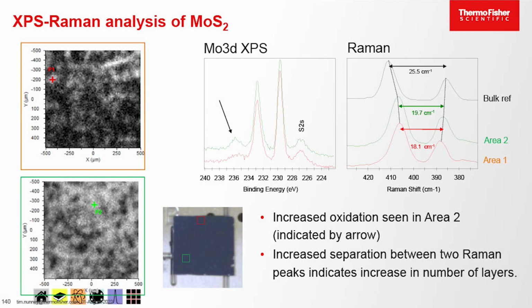So if we have a look at another area on the sample, so this is our original area here in red, and this is another area down here, much more signal down here. We can see much more, but we see a larger separation in the Raman spectra for the separation of those two peaks. So we've gone from 18 wave numbers here to nearly 20 wave numbers down here. And if we look in the XPS data, so this is a sulfur peak, this is our molybdenum disulfide in this chemical state, but there's also another doublet here, which is molybdenum oxide, and it's quite weak in this area, and it's a bit stronger here. So we're seeing some oxidation of the molybdenum at this point as well.